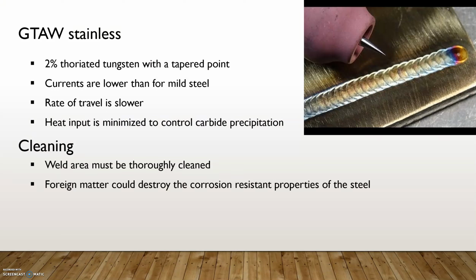Page 4, 2% thoriated is used with a conical end. Currents are lower than they would be for mild steel so that you do not overheat the chromium in the material, which could result in carbide precipitation. For cleanliness, it's said the 3 C's, clean, clean, and clean, should always be thought of. If the material gets dirty, it gets really hard to weld. Oxides from interpasses will slow down welding and make things much harder than they have to be.